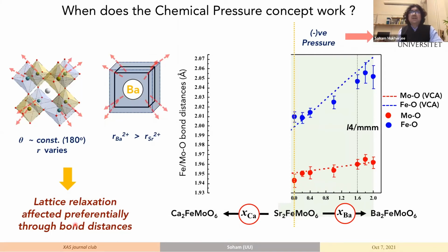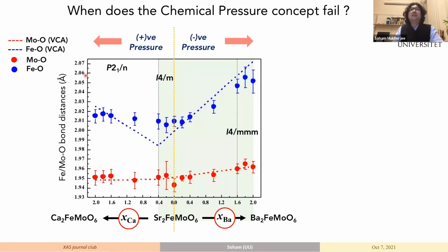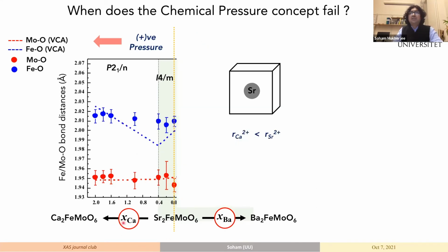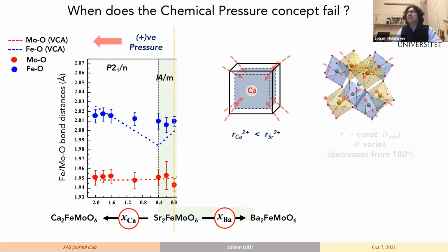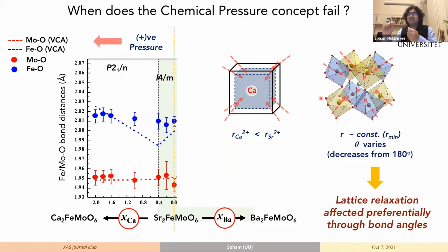chemical pressure predictions. But the moment you look at the positive pressure end, where you are putting in the calcium, what happens is that the distances, they're already at their minimal value. Now, when you try to put in a smaller atom to compress a unit cell, what it does, it buckles the bond angle because the distances cannot go any shorter. Now, the lattice relaxation is affected preferentially through bond angles and not through distances.